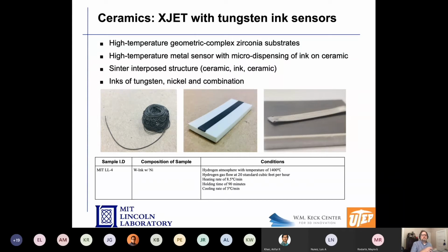And you could do that to make an antenna or a strain gauge, but an interposed structure that could go up to 1,000 degrees C with no problem. And if you think about it, there's a lot of applications like jet engines, gas turbines. There's just a lot of applications where having a sensor or an antenna would be pretty interesting. You're not going to put a microcontroller in this, because if you did, it would be vaporized at 2,500 C. But these inks and the dielectrics are enough to give you some basic sensor type functionality. And so this is an ongoing project. This is a tough one though, because melting tungsten's tough, and curing and printing ceramics is also tough. So this is a very ambitious project.